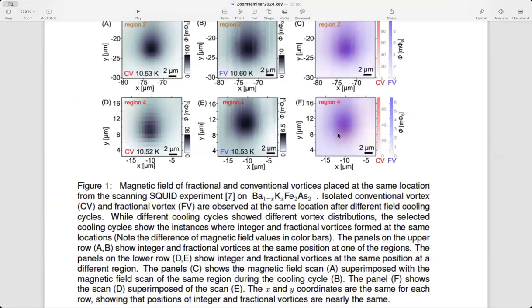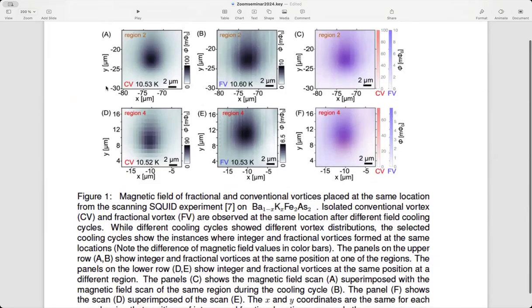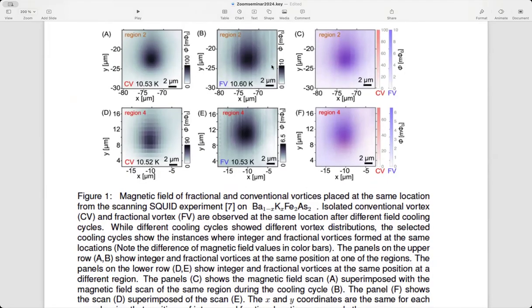So let me show you this example. You can see there are two vortices, and they have an order of magnitude different flux, and they are created at the same position, vortices carrying about 10% of the flux quantum. This is just superimposing these two pictures, showing that these are really true vortices carrying an arbitrary fraction of the magnetic flux quantum, which are mobile objects, not area dependent or this type of thing. And these are the objects which are required in this type of mechanism.